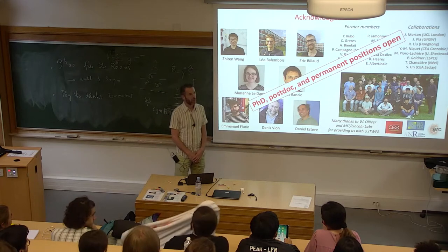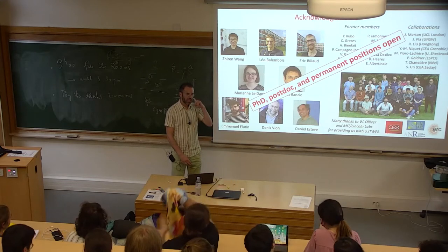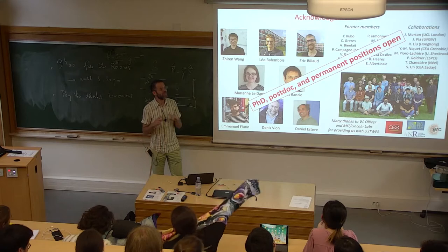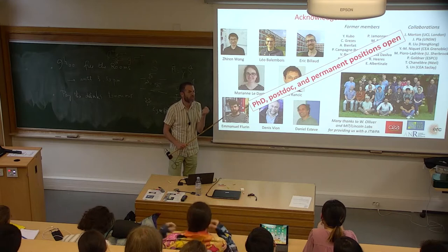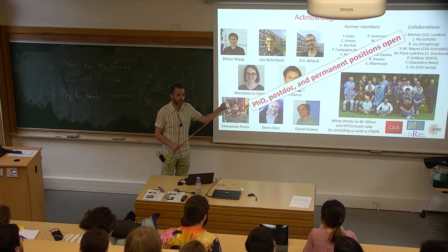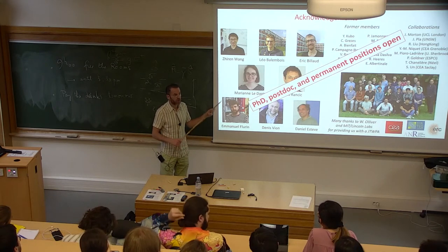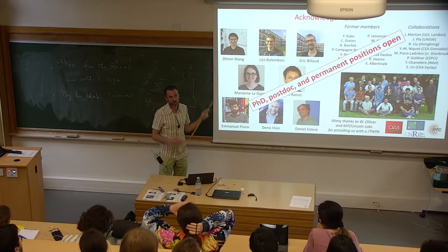Yes, that's a very good question. First, we don't know. This detection method is very special, I have to say. We detect any erbium ion which is in this 100 micron cube volume. This is enormous. All other single spin methods require you to be extremely close to the spin. So probably most of the atoms that we detect are really in the bulk, maybe 300 nanometers below the surface. All I can say is that so far we really do not see any surface effect, which is not surprising given that we have a very big detection volume.